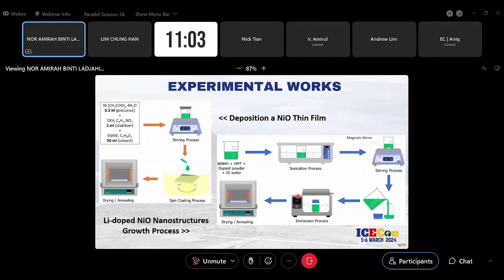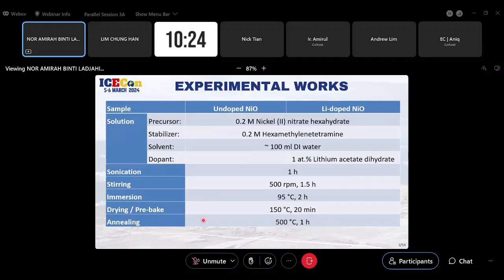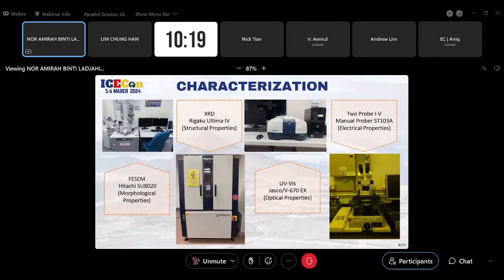To be more detailed in the nickel oxide deposition process, we use a mixture of nickel acetate, diethanolamine, and 2-methoxyethanol. This will act as a precursor, stabilizer, and also solvent, respectively, to form a thin film. So this is the process. While this picture represent the growth of the nanostructure of both undoped and lithium doped nickel oxide. So this is the parameter of the experiment. For the samples characterization, we are using these 4 equipment to examine the properties of samples. So there are 4 properties that we use to examine the characteristic of this sample.